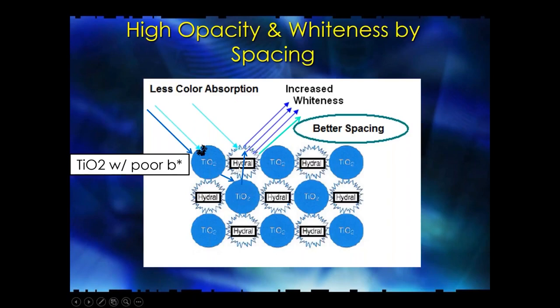The ideal spacing of the titanium dioxide is a quarter micron in size. So if you can squeeze another particle in between, either a hollow one or a low refractive index particle, in this case I choose hydrated alumina because it's very pure, and it's also pure alumina, so it has complete compatibility with a surface treatment on the TiO2. You can get increased whiteness and better spacing. So this is very important.